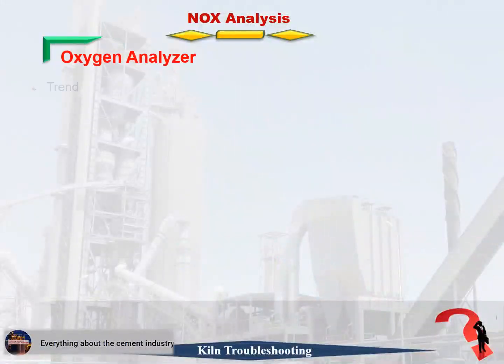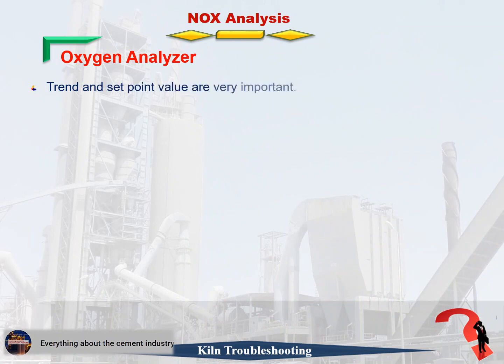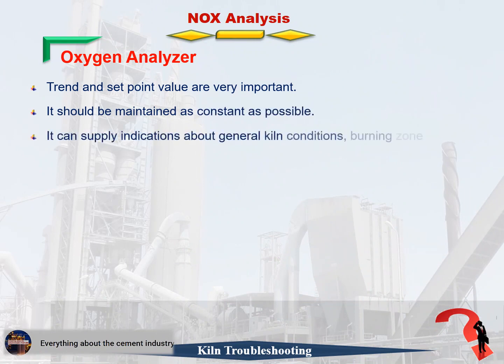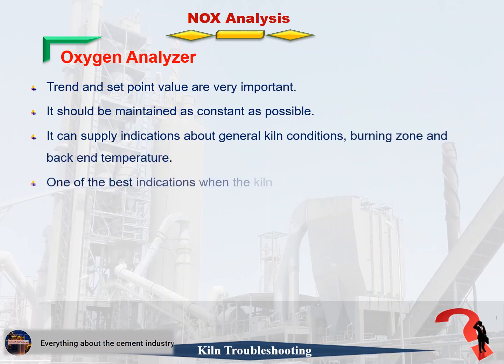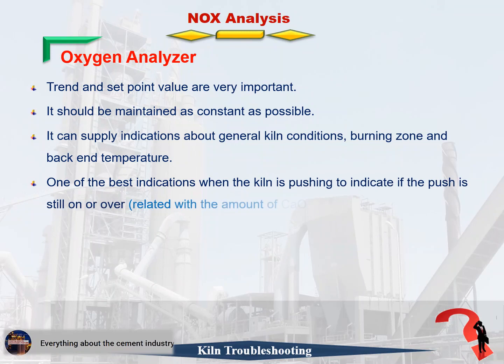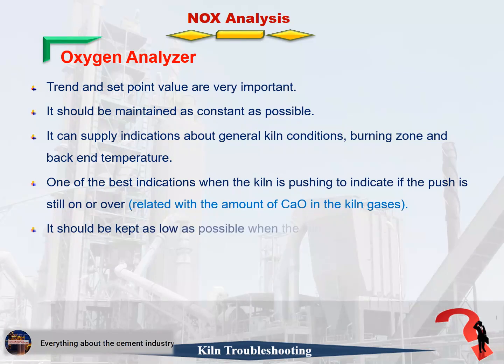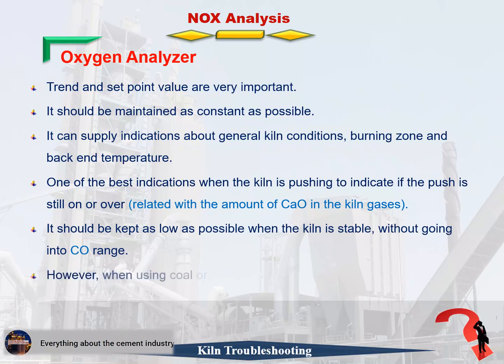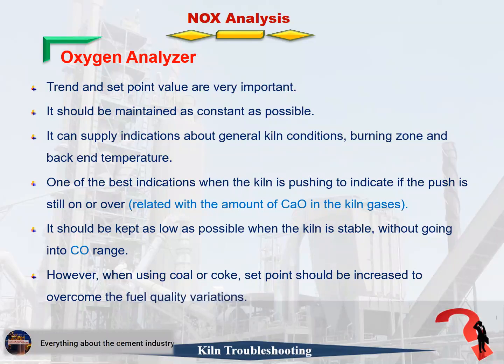Oxygen analyzer. Trend and set point value are very important. It should be maintained as constant as possible. It can supply indications about general kiln conditions, burning zone, and back-end temperature. It is one of the best indications when the kiln is pushing, to indicate if the push is still on or over, related to the amount of CaO in the kiln gases. It should be kept as low as possible when the kiln is stable, without going into the CO range. However, when using coal or coke, the set point should be increased to overcome the fuel quality variations.